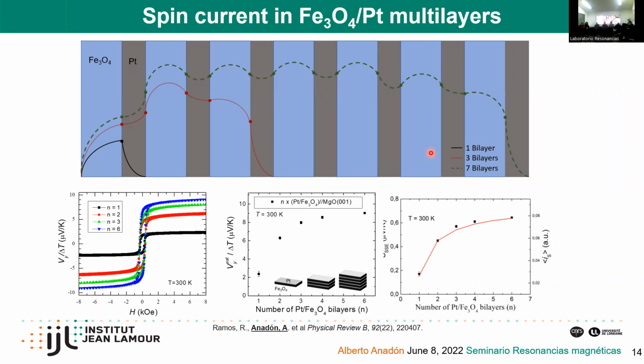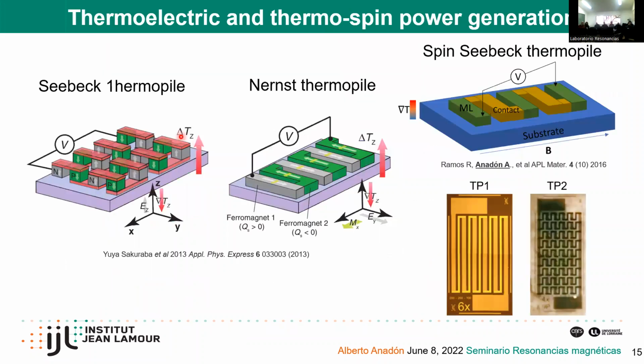So based on the system that I showed at the beginning of the introduction, we can do Seebeck thermopiles based on the Seebeck effect, or if we are using the Nernst effect, we could do these Nernst thermopiles. And for the spin-Seebeck effect, we can use a similar design as the Nernst thermopile. So this is what we did. We did two different designs.